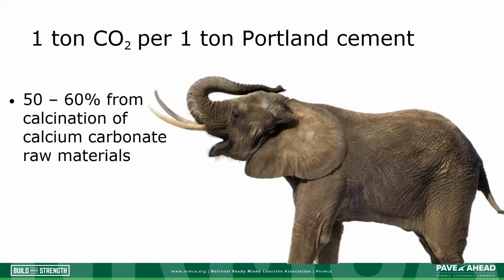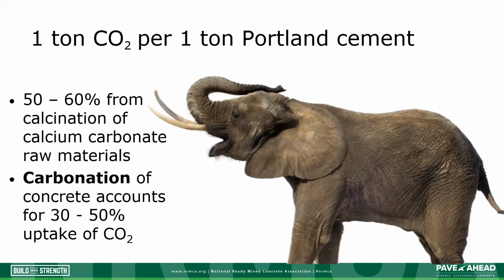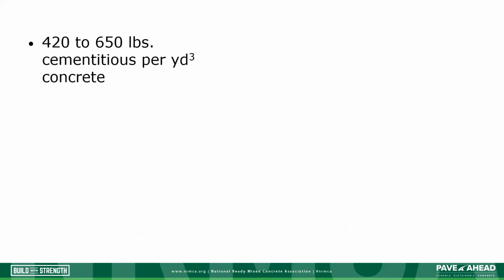50 to 60% of the CO2 produced comes from the calcination of calcium carbonate raw materials and has nothing to do with the consumption of fossil fuels. Additionally, concrete actually absorbs CO2 through a process called carbonation. Over its life, concrete can absorb enough CO2 to offset 30 to 50% of the total CO2 initially produced.